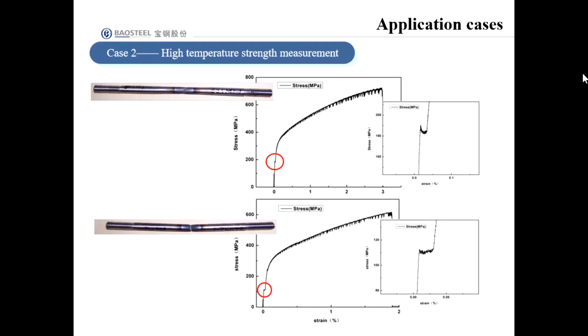The stress-strain curves can be recorded when the specimens are pulled at a certain temperature, so we can get the yield strength of steel with different chemical composition designs. By analyzing and comparing the results, the steel with the chemical composition that meets the requirements of high temperature strengths can then be selected. So it is very useful for us to select the steel's chemical composition.